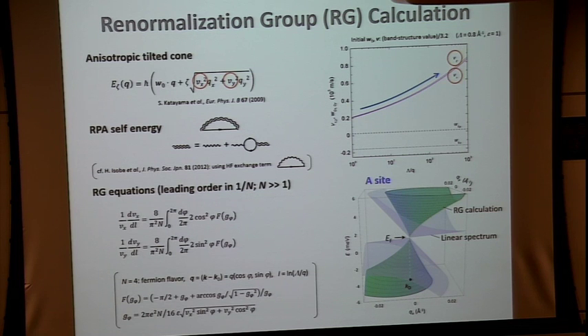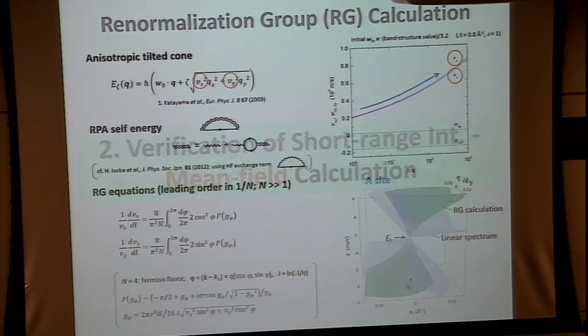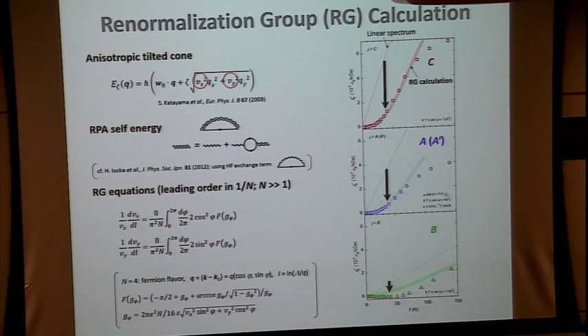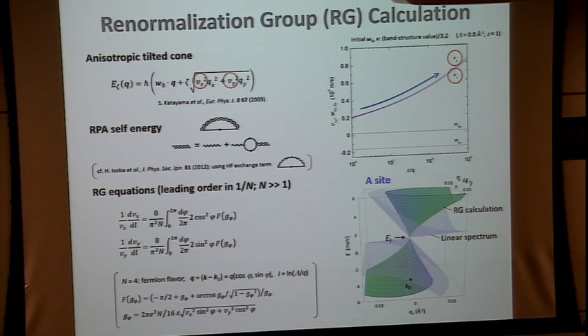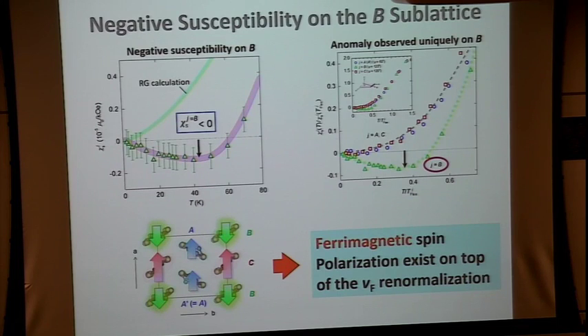However, in reality, the real cone is like this. So this cone is reshaping due to the long-range Coulomb interactions. But you see, there is a serious, very sizable discrepancy between this renormalization calculation and the experimental data. As for the B site, A and C are okay. This is a non-negligible difference. What is the origin of this? And my colleague calculated the, okay, before that, let's take a look at the data more closely.